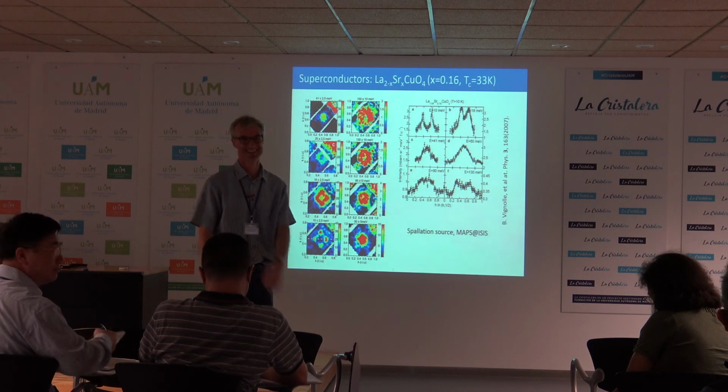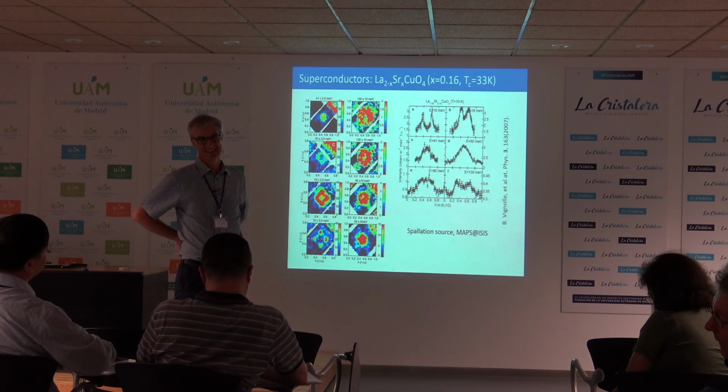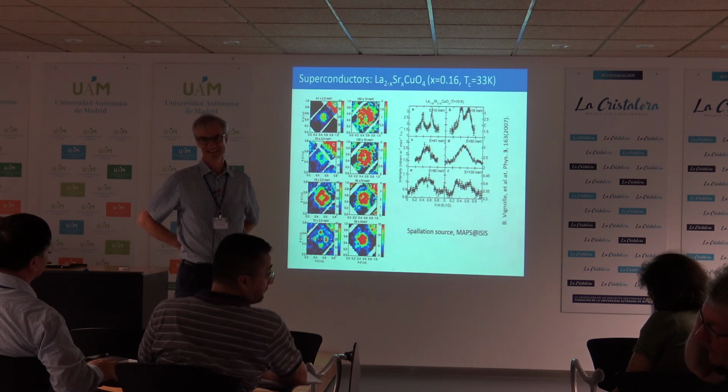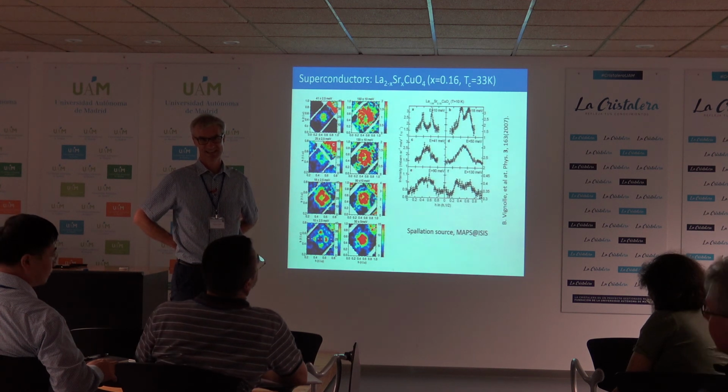Right, yeah. The overall structure of the magnetic excitation spectrum is universal. It's in all cuprates, and then some of the low energy excitations are different in different compounds. That's also reflecting the proximity of the stripe state. In this system it's almost stripe ordered, even at optimal doping.